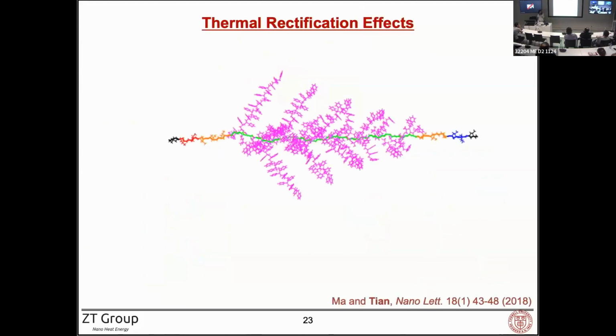So we looked into polymers for potential thermal diode behavior. People studied asymmetric carbon nanocones and asymmetric graphene nanoribbons before, but I wondered if we can also observe this thermal rectification effect in polymers. Particularly, we looked into these tapered bottlebrush polymers, which have a highly extended backbone. Here we use polynorbornene, stabilized by the side chain here, which is polystyrene. The side chain length is systematically varied to form this cone shape.